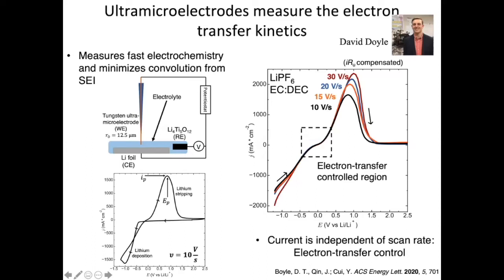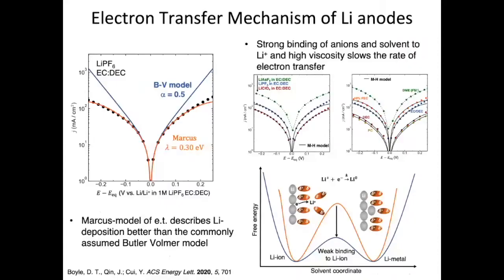So now you look at this, zoom in and look at this range of the small voltage window, it's independent of scan rate. This is the regime right now. It's electron transfer control regime. You are not controlled by the mass transfer, the mass transport. This microelectrode really gives the advantage to study the charge transfer free of a mass transfer limit. So this turned out to be quite exciting for us to go into the detail to analyze this curve within the electron transfer limit.